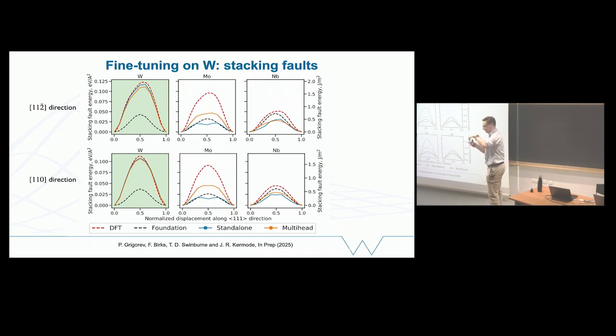This is stacking faults, so taking a crystal and sliding half the crystal over itself. Out of the box, the foundation model is really underestimating these stacking fault energies. It's not surprising there aren't many defects in the Materials Project database, so it hasn't got information on which to do this. But this was quite a good success of the fine-tuning. I put in a few configurations like this, and I improved significantly the description of the stacking faults, which was the thing that I cared about in this configuration.